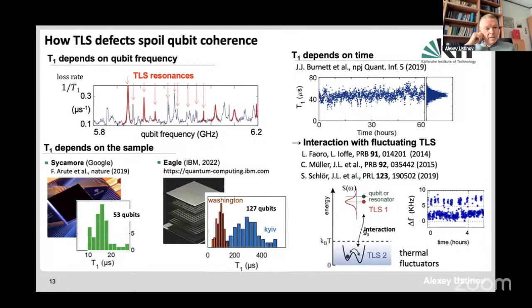So if you measure the lifetime of the qubit excited state as a function of frequency, you'll find a lot of bumps, and that's what you see here on the top on the plot on the left. The bumps are there due to the coupling to the microscopic defects. And this very bumpy frequency dependence leads to a large spread of parameters of artificial two-level systems fabricated in superconducting processors.